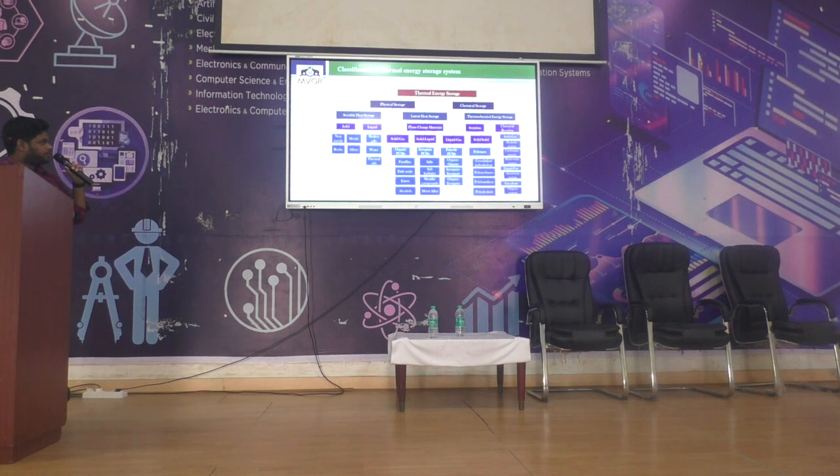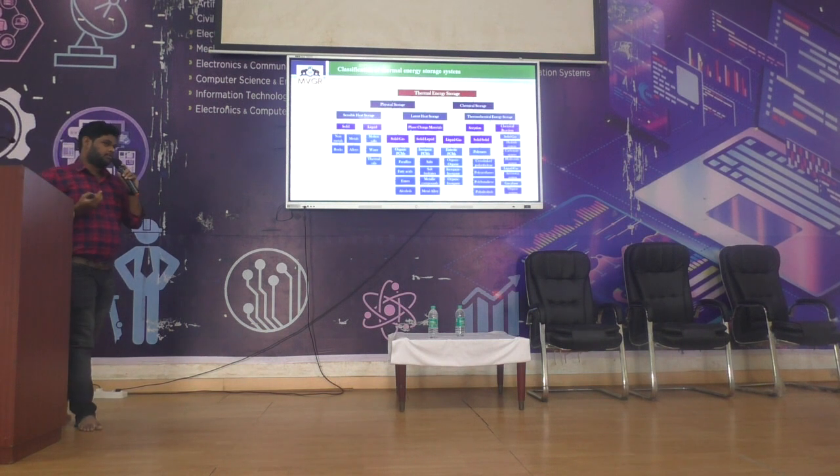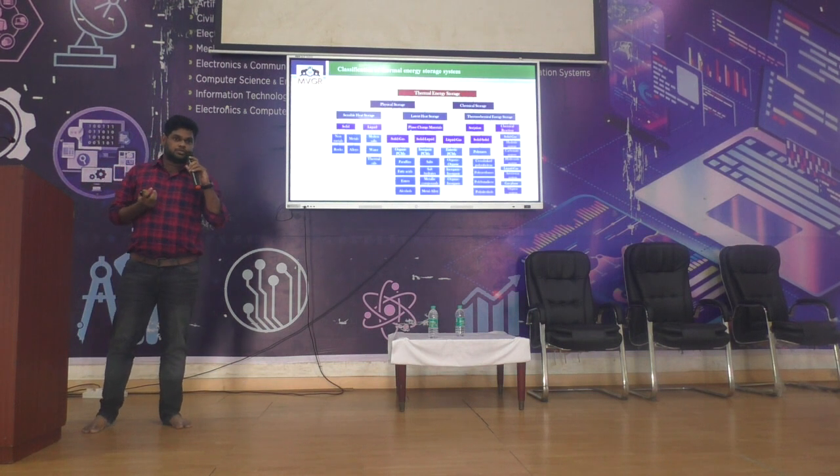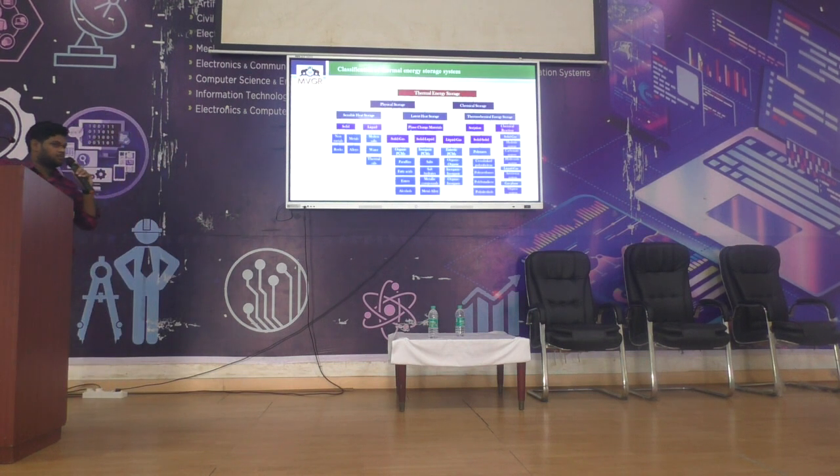Why? Because with solid to gas and liquid to gas, the gas has a higher volume, so storage volume issues arise. That is why we focus only on solid to liquid and solid to solid. Again, solid to liquid is classified into organic phase change material, inorganic phase change material, and eutectic phase change material.